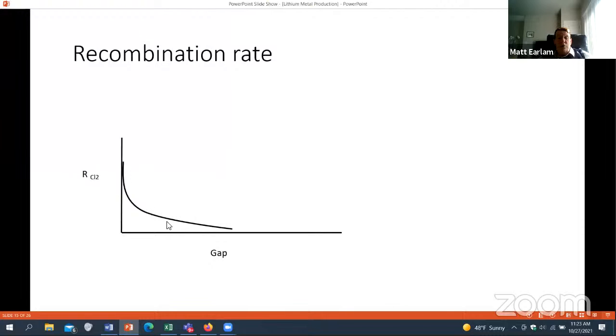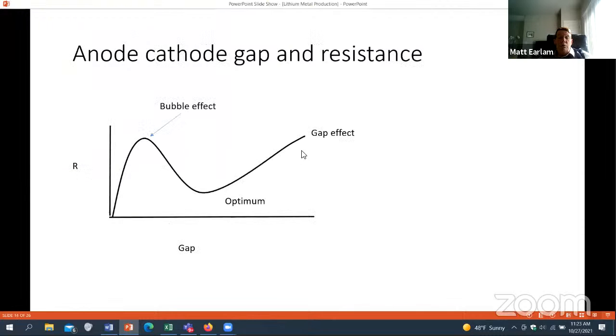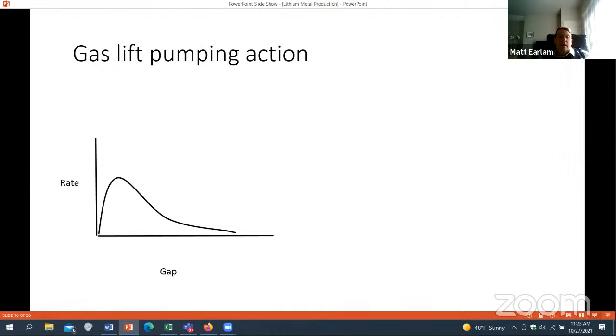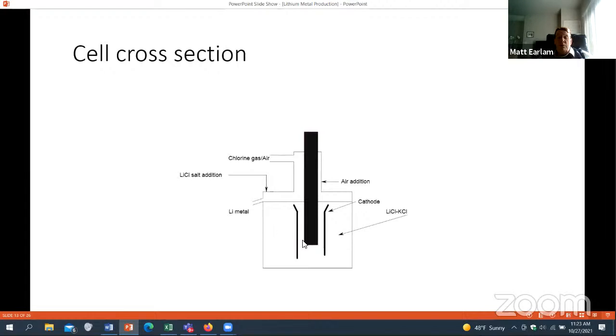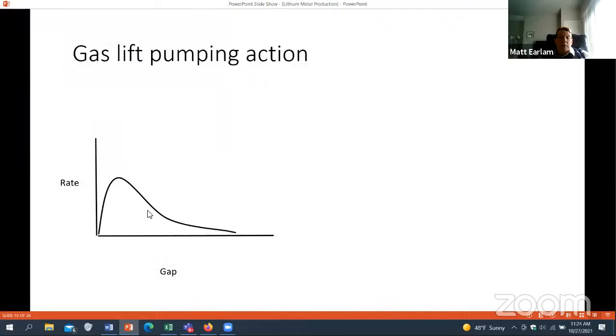So you want to increase the gap for current yield, but you want to not make it too large because then the resistance starts to go up and your energy consumption starts to go up. Also, your heat production starts to go up, and so you have to manage those two things in conjunction with each other. And then the other thing that happens is that you have an anode gas lift pump. So as the chlorine bubbles evolve here, it pulls electrolyte up and over, which is important because it helps you sweep the metal off the cathode through collection. But if you get too close, your pump rate basically stops because you don't have enough electrolyte to pump.